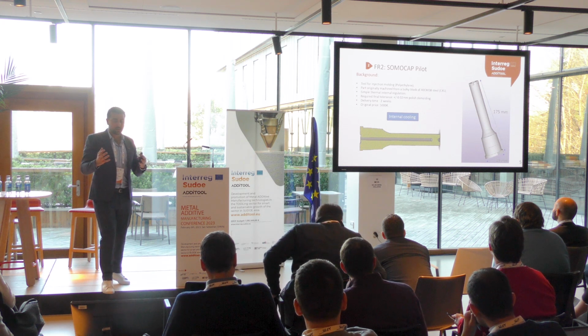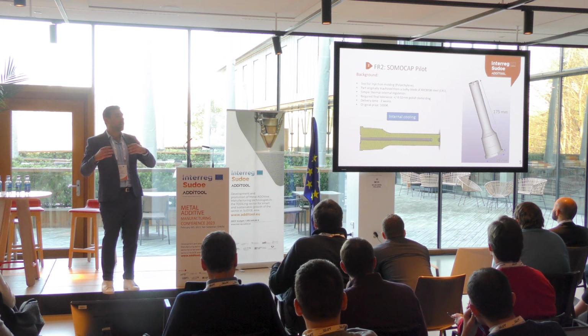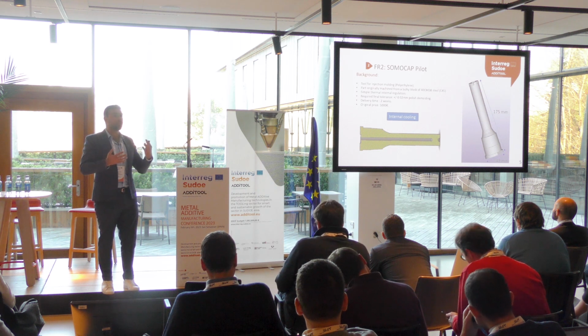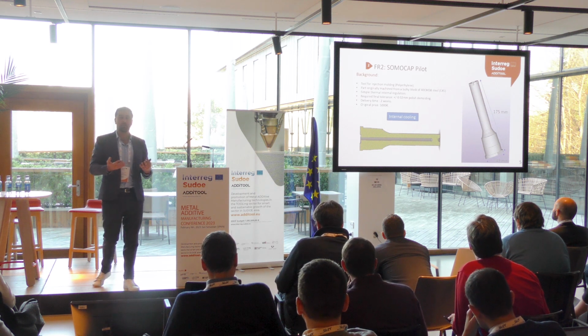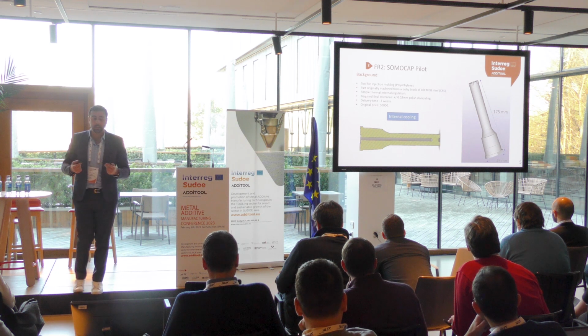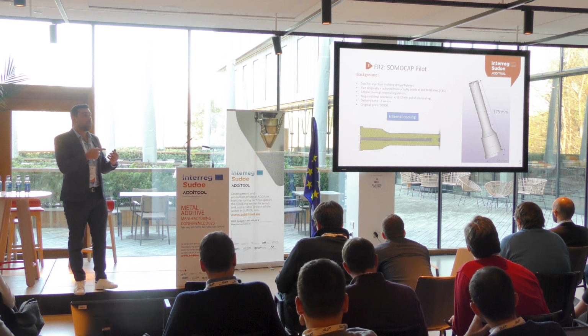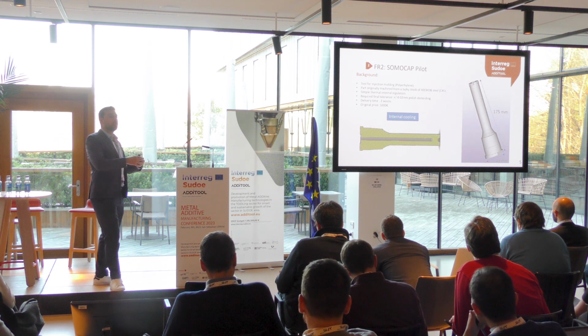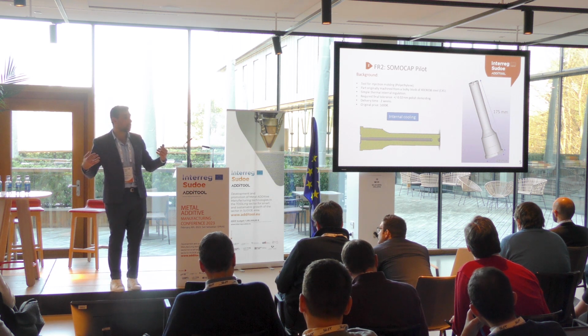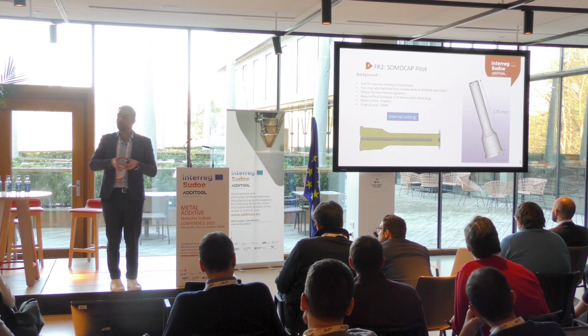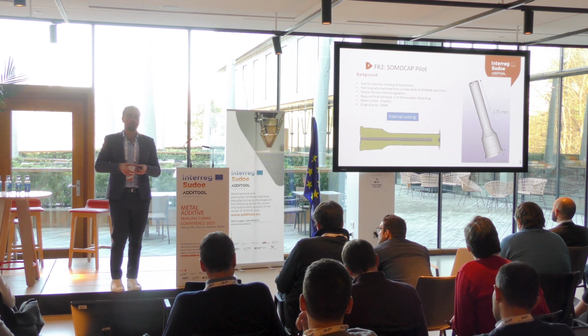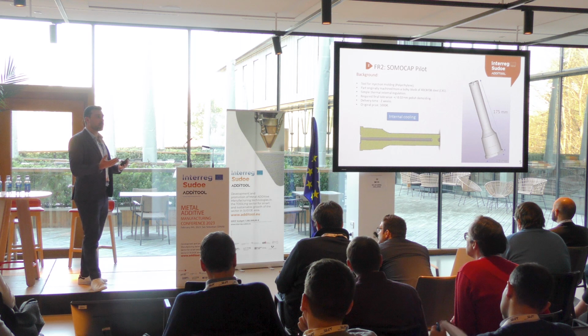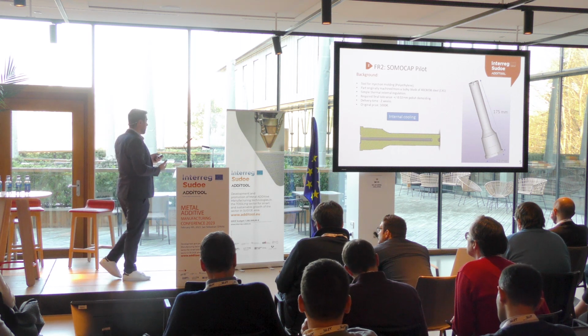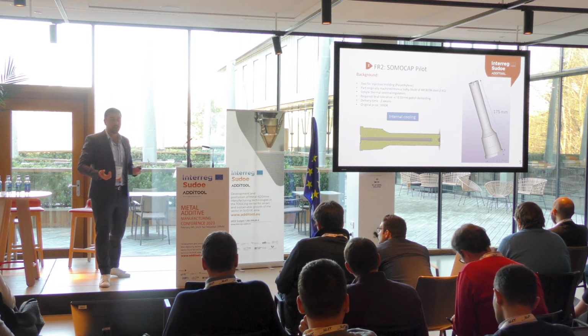Originally, this part from a bulky block has a simple hole, so no real good optimization of the cooling. And when we are cooling the polymer part, when we remove the core of the mold, the hole is not cylindrical, but a little bit ovoid, okay? Because the cooling was not controlled and not efficient.